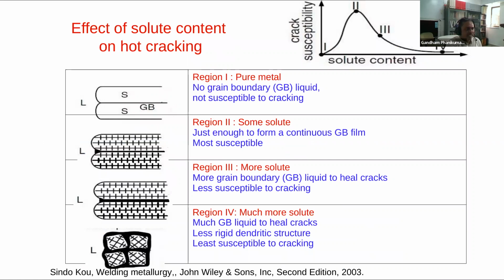Okay, so the physics of how it is happening is here. If you take the solute availability, the liquid that is able to move in between the grains of the solid can go on and heal the cracks, and if it doesn't, then there's a problem. Of course, if you have equiaxed grains, there is no problem at all, because there is no channel that can be cut off. The liquid is all around the grains, and therefore it will be least susceptible to cracking. So equiaxed microstructures of fine grain size are least susceptible to cracking, whereas columnar grains, which are very long and in the direction towards making a single crystal print, would be highly susceptible to cracking, because they may prevent the liquid from reaching the channels, as bridging can happen here, and then the channel is cut off. So columnar growth is more susceptible to cracking; equiaxed growth is less susceptible to cracking.